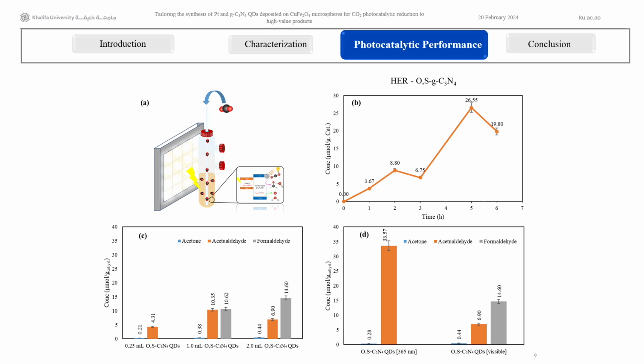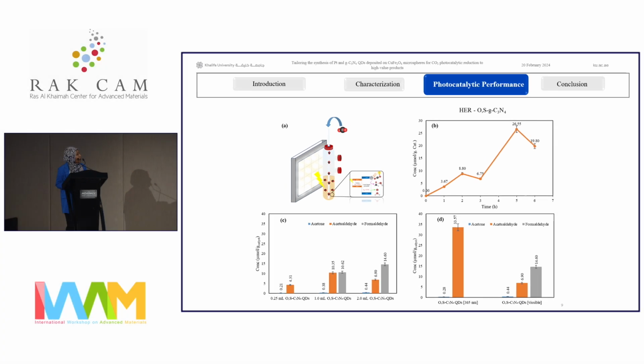So we know that we managed to produce hydrogen just from using the quantum dots. Then we tried different concentrations of the quantum dots, and we formed different products, mainly formaldehyde, acetaldehyde, and acetone. The highest concentration we obtained was 14 micromole per gram using this concentration, and it was highly selective for formaldehyde. Then we tried the effect of using different wavelengths. We tried the UV at 365 nanometer, and visible light. And then we found that when we use this wavelength, we have a higher yield of acetaldehyde.